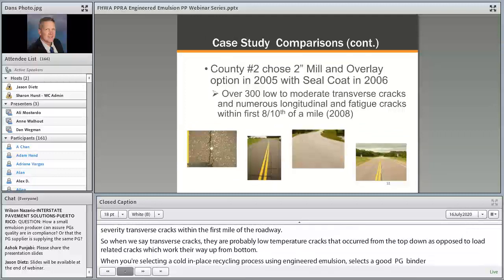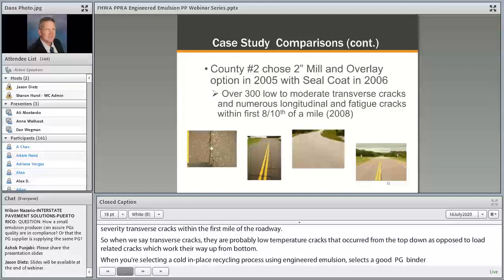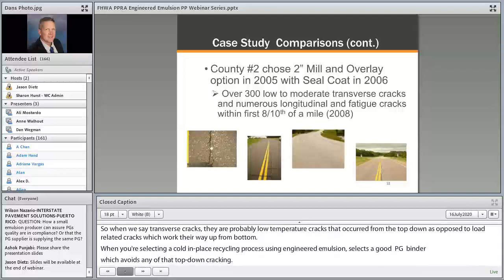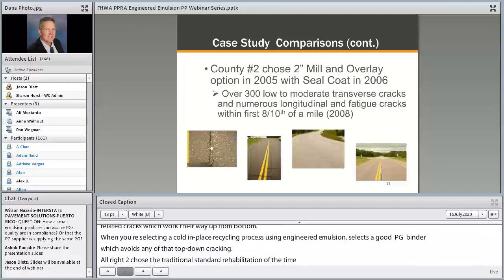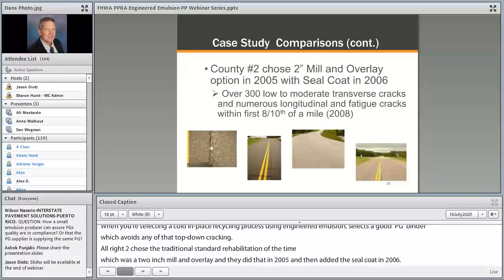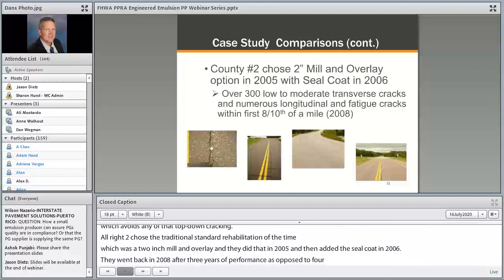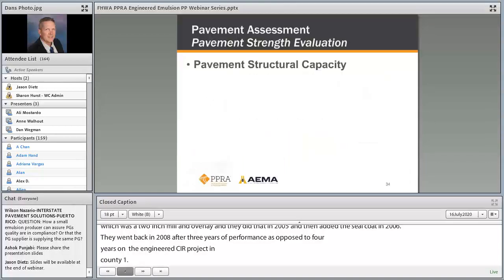County 2 chose the traditional standard rehabilitation at the time, which was a 2-inch mill and overlay. And they did that work in 2005 and then added a seal coat to it in 2006. They went back in 2008 after 3 years of performance, as opposed to the 4 years of performance on the engineered CIR product in County 1. County 2 ended up with over 300 low to moderate transverse cracks and numerous longitudinal fatigue cracks within the first 0.8 of a mile.